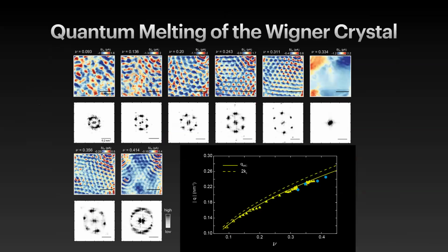So you can compute from the data the structure factors of the electron density of states. If you do that for the incompressible state, you get nothing. And then you get a beautiful Wigner crystal. And what's interesting is the places where you go near the incompressible states.